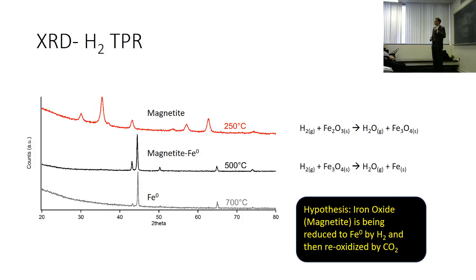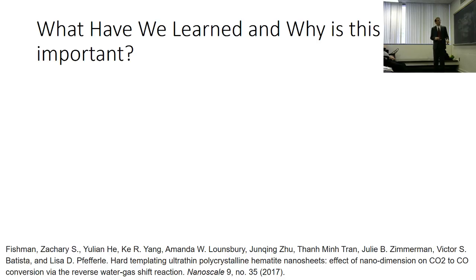The nanowires are actually better at retaining their nanostructure. There's a balance here, it seems, between reactivity and stability, which is important for reverse water-gas shift over hematite, over iron oxide nanosheets and nanoparticles.